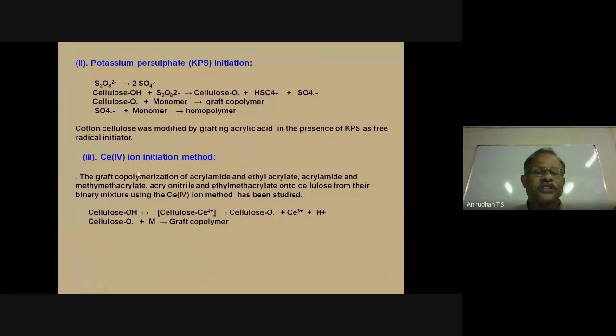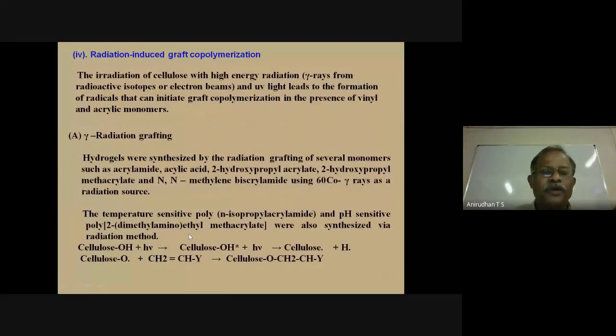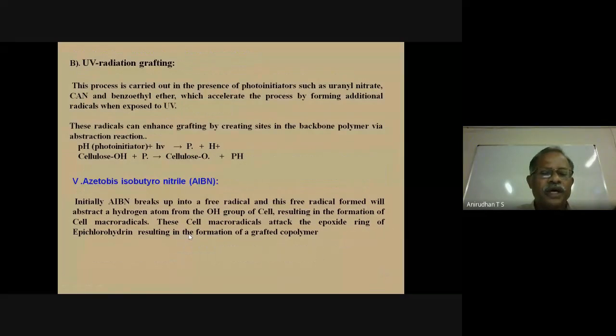Similarly, ceric ammonium nitrate is also used as an initiator, where ceric ammonium nitrate reacts directly with cellulose, and we have a macro radical, and that macro radical reacts with monomer to form a graft copolymer. I want to stop here because there are different methods. Another initiator is azobisisobutyronitrile. It's a very important initiator because here also we first want to prepare a radical.